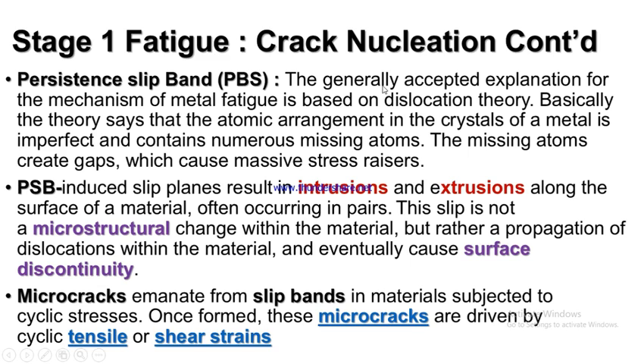Like I put here, it is generally accepted that the mechanism of metal fatigue is based on dislocation theory. The theory says that the atomic arrangement in the crystals of a metal is imperfect and contains numerous missing atoms, and the missing atoms create gaps, which cause massive stress risers. Those dislocations that occur in the material, which can make the material plastically deformed, cause stress risers or stress amplifiers in the material, which will definitely lead to persistent slip bands taking place, and which will lead to surface discontinuity.